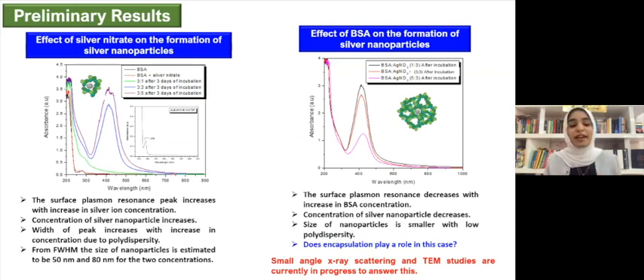We used the full width half maximum method to estimate the size of our nanoparticles to be about 50 nanometers to 80 nanometers for both concentrations. On the right-hand side, we investigated the effect of BSA on the formation of silver nanoparticles. Here we varied the concentration of our BSA and kept the concentration of our silver nanoparticles constant.